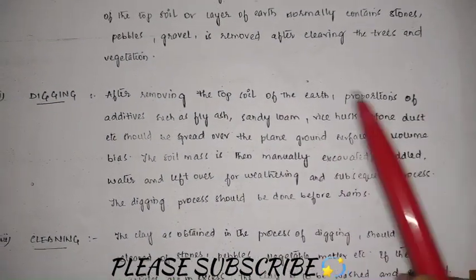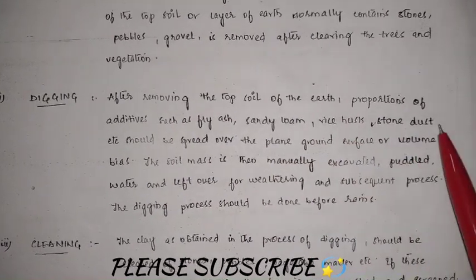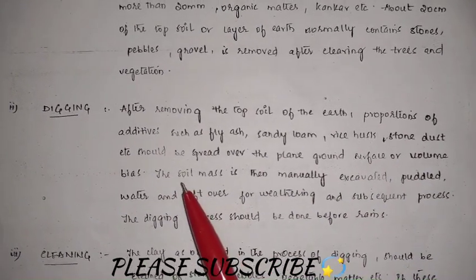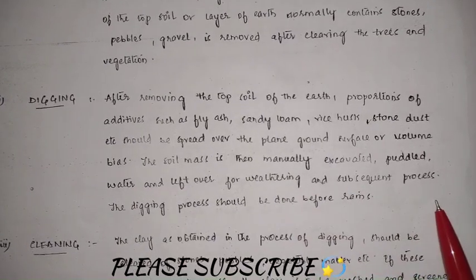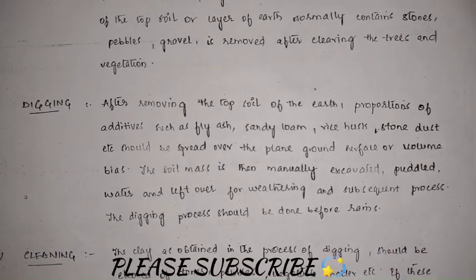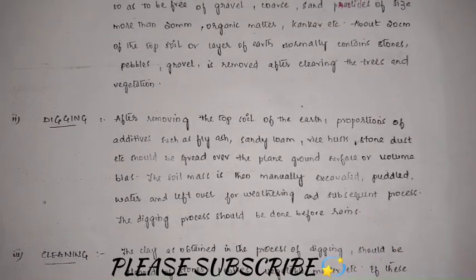Coming to the next one, we are digging. After removing the top soil of the earth, proportions of the additives such as fly ash, sand, sandy loam, rice husk, stone dust, etc. should be spread over the plain ground surface or volume basis. The soil mass is then manually excavated, puddled, watered and left over for the weathering and subsequent process. So the digging process should be done before rains. So here the soil below 200 mm is dug out preferably before rains.